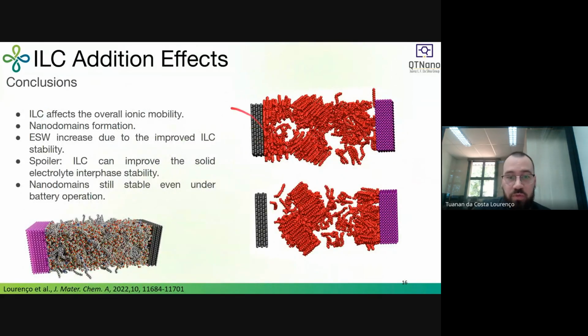So as a conclusion of this work, we have seen that the ionic liquid affects the overall ionic mobility. Also, we see formation of nanodomains. We saw an increase in the electrochemical stability of the electrolyte. And in another study that we had, we saw that when we have cations in ionic liquids with large chains, these cations tend to be more stable against reduction. So that means that if we use these cations in electrolytes, we can widen the electrochemical stability.